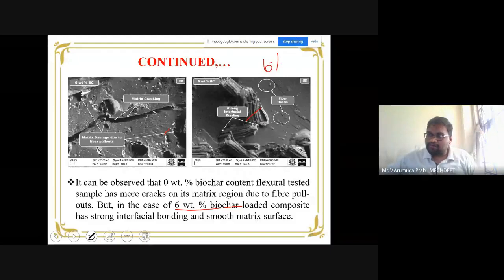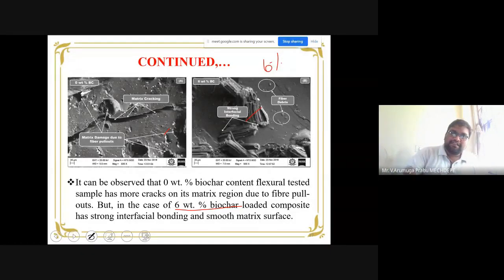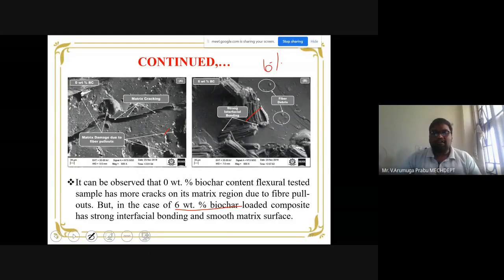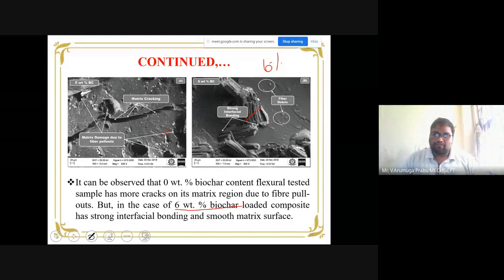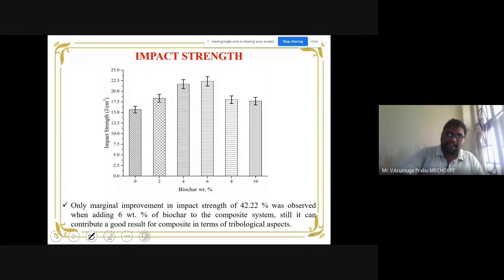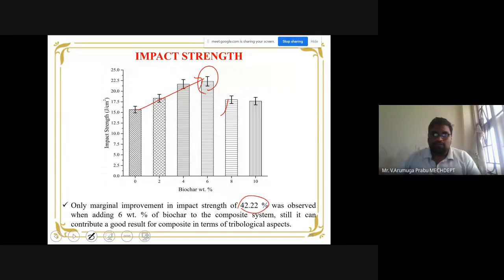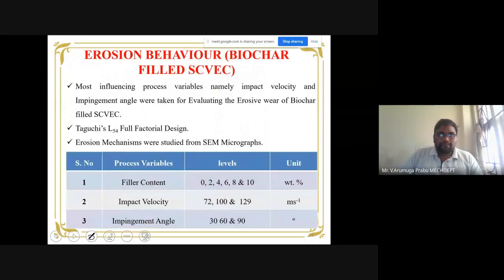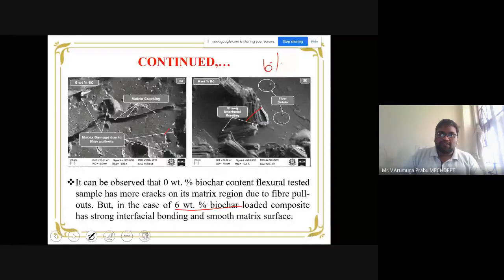In these scanning electron microscopy studies, I am able to notice that 6 weight percentage biochar has a strong interfacial bonding between the matrix and the filler that will automatically hold strongly, in such a way that the fracture gets avoided, the failure gets avoided, which is evident from the same image. Again, same case, at 6 weight percentage the impact strength touches the peak, and the increase is about 42% higher than the one without the biochar. And with that, the mechanical properties are over.